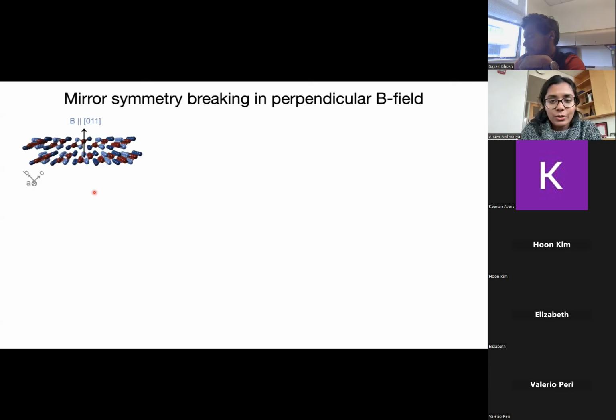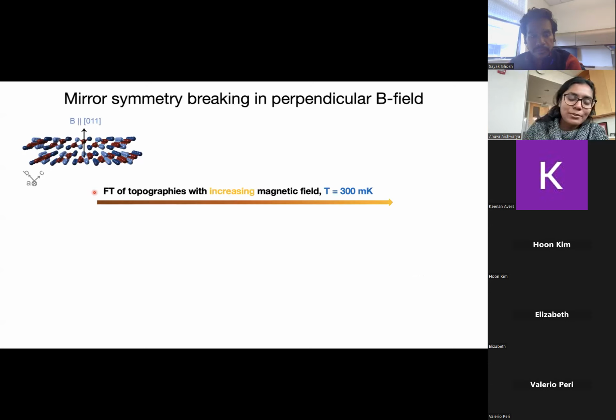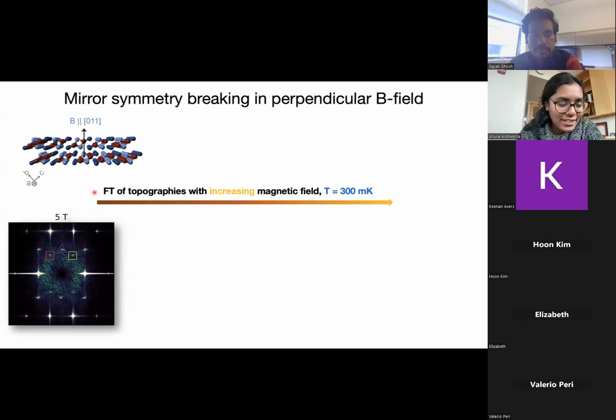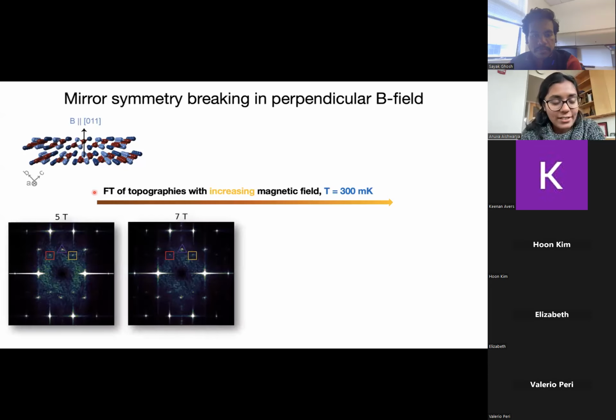Anyway, next we go on to track its field dependence. In principle, we can apply a perpendicular magnetic field with our STM, and in principle, it should not do much because we can only go to fields up to 10 to 11 Tesla. However, we did it anyway because there was nothing much to do after this. So now I'm going to show the Fourier transform of topographies with increasing magnetic field below TC. So 5 Tesla, 7, it gets weaker.